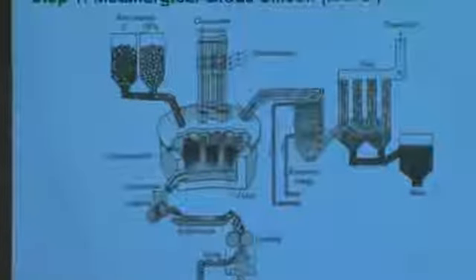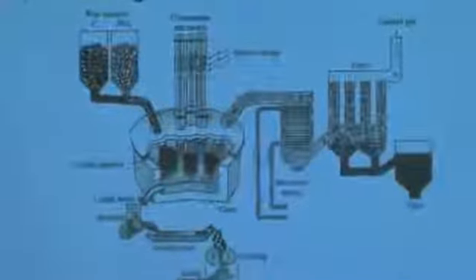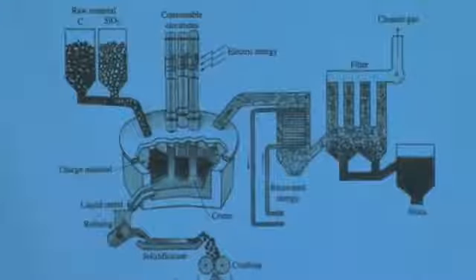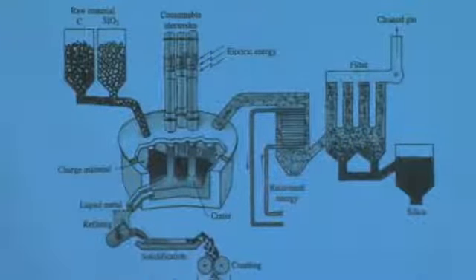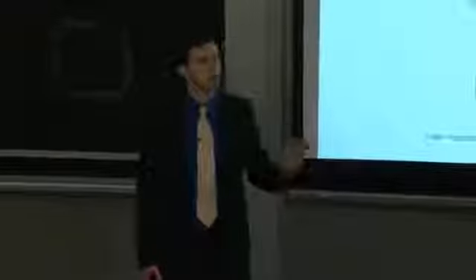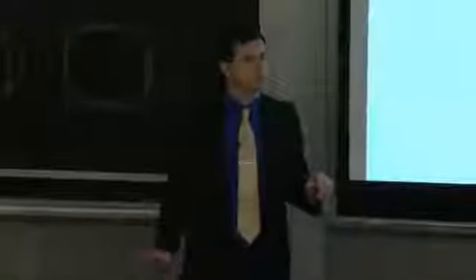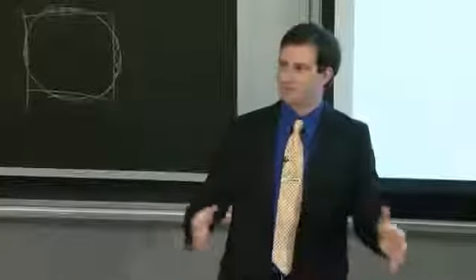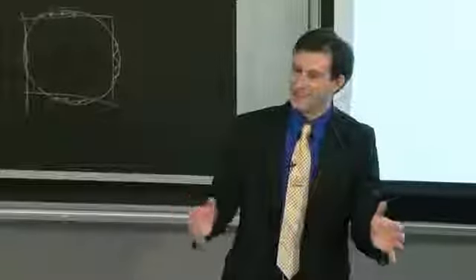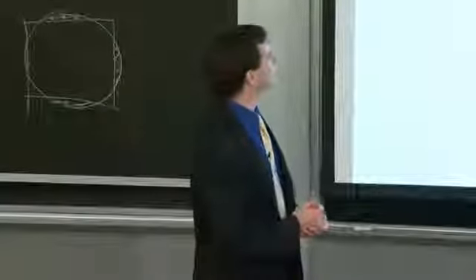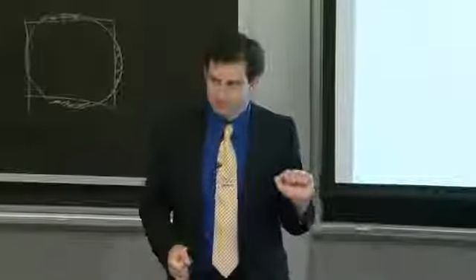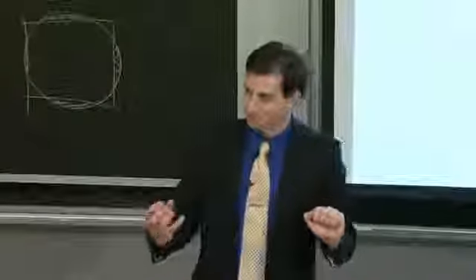That's the SiO2 input. And the C input over here on the left-hand side, carbon. So typically what is used in the PV industry is either a fast-growing wood source, like eucalyptus or southern pine, right? Northern pine tends to be slower growing, but eucalyptus and southern pine both tend to be fairly fast growing. You can tell by the spacing in the rings if you chop the tree down and do a cross-section. Or coal, so carbon, essentially.